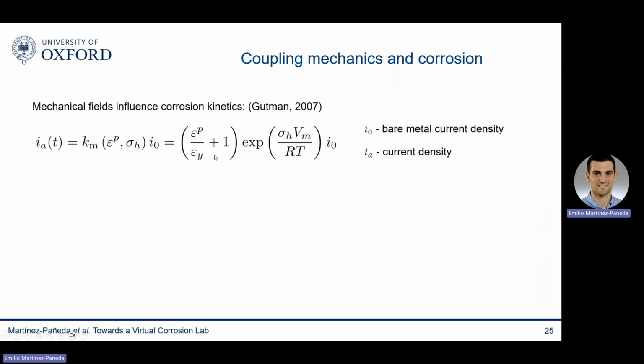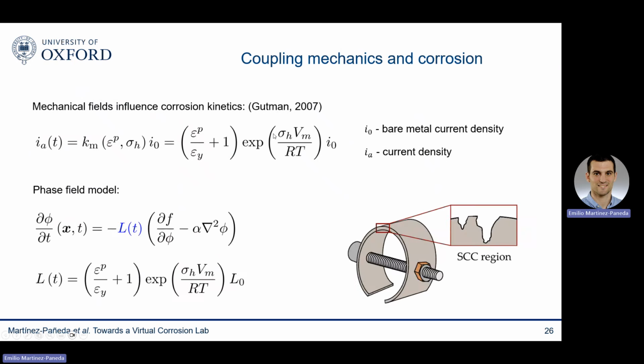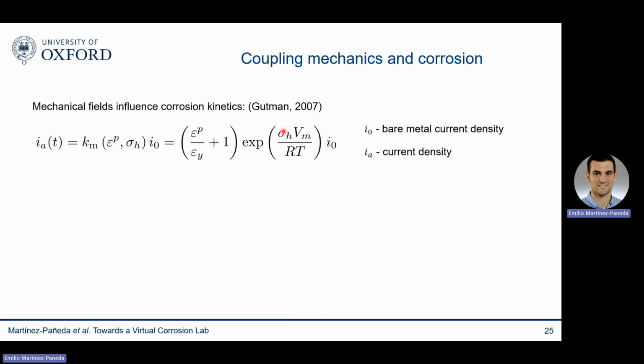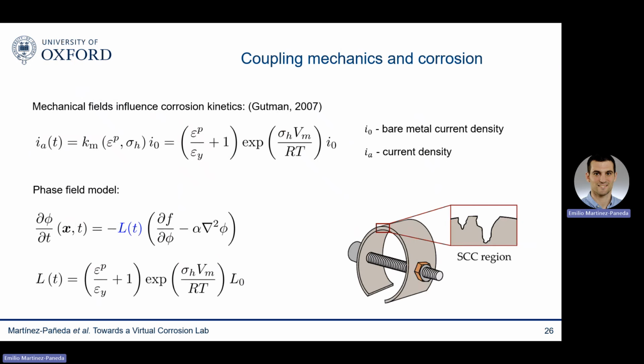As a mechanician, the first ingredient that I was keen to add was the role of mechanics. And mechanics can impact corrosion in two ways. One is by enhancing corrosion kinetics, as nicely described by Gutman. As you can see here, the corrosion current density is enhanced by plastic straining and also by the hydrostatic stress. And we can easily incorporate this into our model because the mobility coefficient, the L parameter, is proportional to the corrosion current density. So we solve the mechanical problem, as you do in any regular finite element code, and bring that information, those hydrostatic stresses and plastic strains, into L, which is no longer a constant.